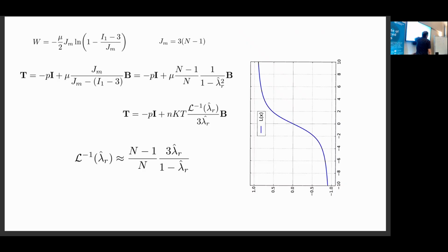So what does the Padé approximation mean? If I have a function, I can do the Taylor approximation, but I lose all the singularities. Here I have a singularity which is central, because I have to predict that when I approach the final length, the force has to blow up. And to approximate this function, I have to use a rational function, a ratio of polynomials. And as you see, this is a first order polynomial, this is a first order polynomial. And if I do the Padé approximation of this function, I obtain exactly the Gent model. And Gent was not aware of all that. He was just imagining, just by intuition.